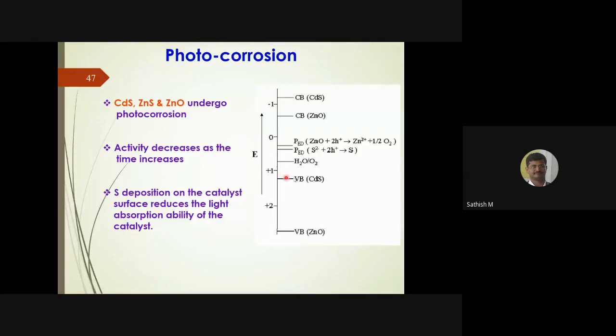So these holes will be absorbed by the sulfide ion. In cadmium sulfide, you have the S 2- sulfide ion. That ion will absorb these holes and then deposit as sulfur. So if you use cadmium sulfide for several hours, there will be a dissolution of sulfide ion. Once the sulfide ion comes out, the cadmium 2+ also goes into the solution, and the sulfur will be deposited over the catalyst.